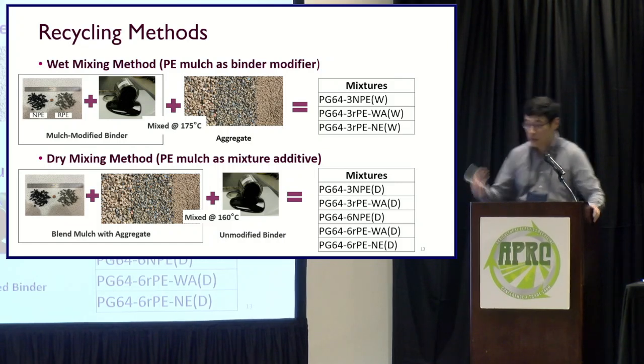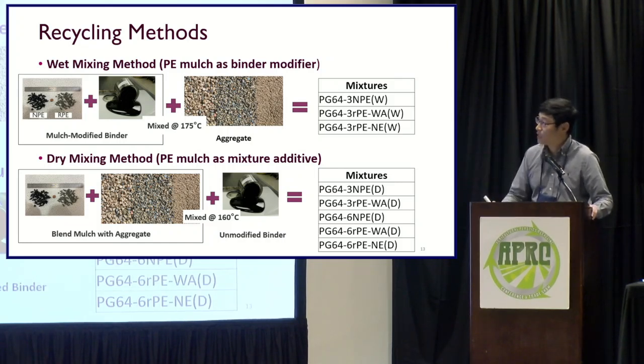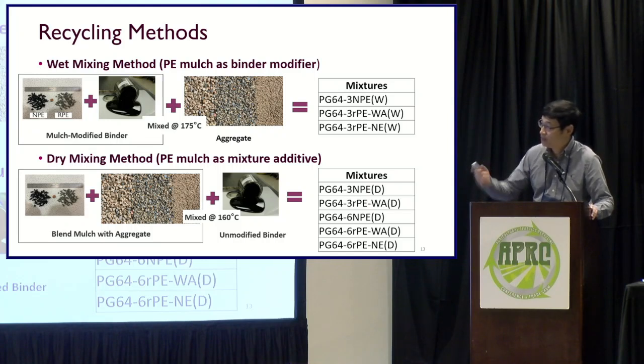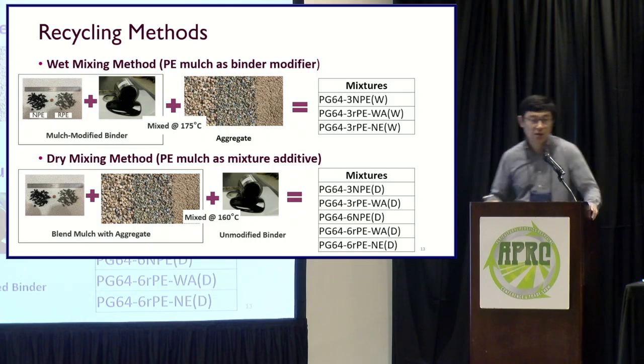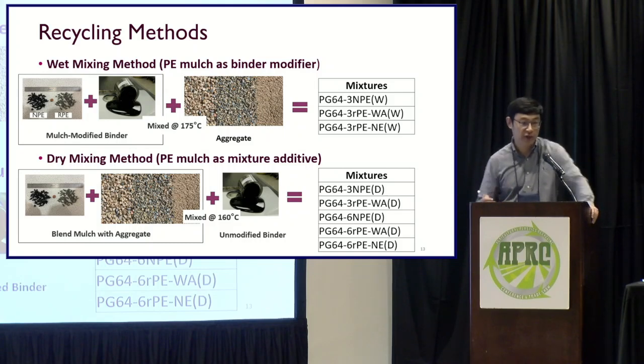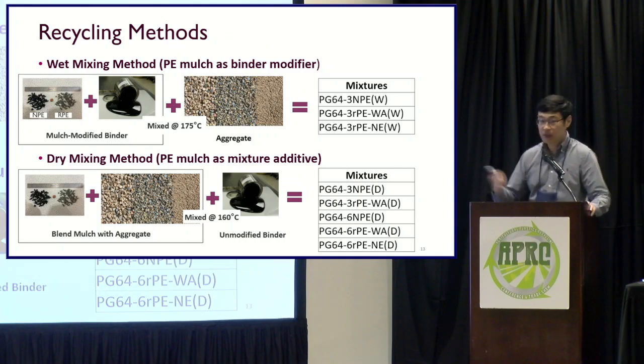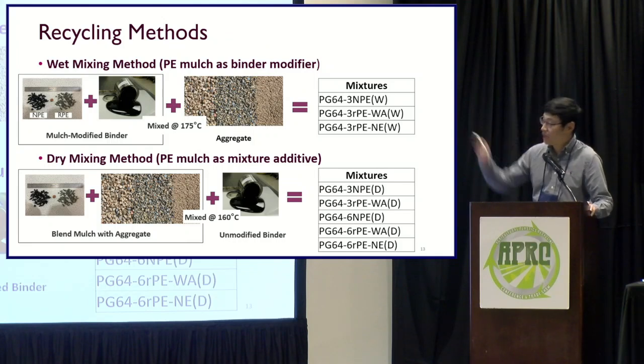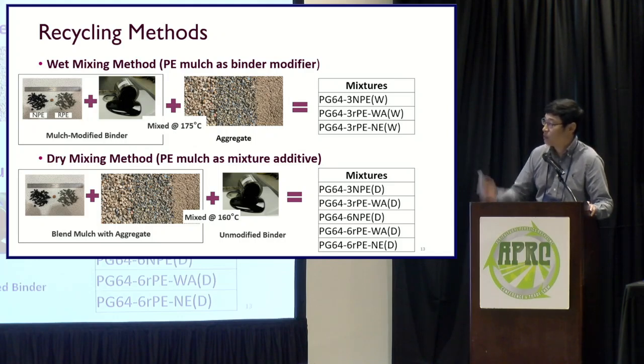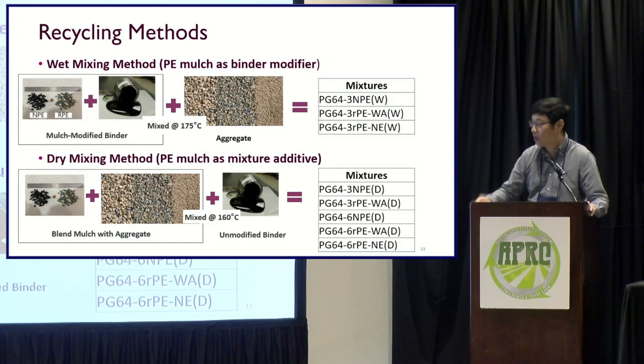And then we came up with these 2 recycling methods. One is called the wet mixing method. So we use a PE mulch as a binder modifier. So we first blend the PE mulch with a binder. So we create the mulch modified binder. Because it's mulch modified, it has a higher stiffness, higher strength, so we have to increase the production temperature. So we mix the aggregate with a mulch modified binder at the temperature 175, and we have 3 mixes. So here's the W over there that stands for the wet mixing method.